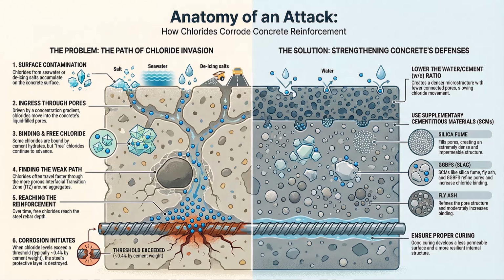When the structure gets wet, the porosity of the concrete allows capillary absorption to rapidly wick chlorides a few millimeters inward. But then, when the wave recedes, the intense sun and wind cause the water to evaporate, leaving the salt behind. Ah, so the salt gets left behind. It does. And this isn't just drying. It causes salt crystallization within the pore structure, and it dramatically increases the surface chloride concentration, the CS, on the face of the concrete. So with every single cycle, the surface salt concentration is being reinforced and increased, creating an even stronger driving pressure for the next wetting event.